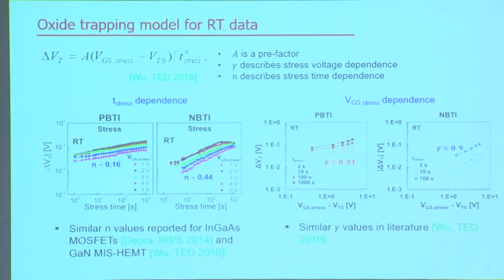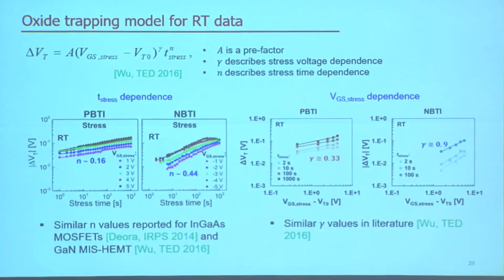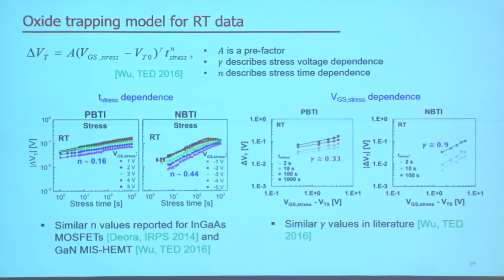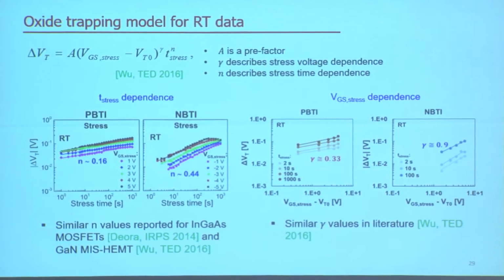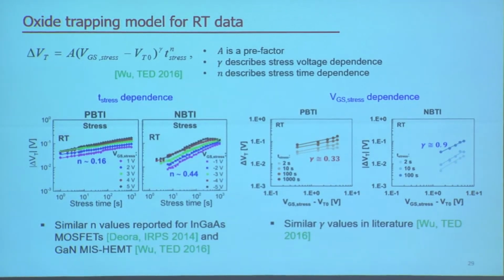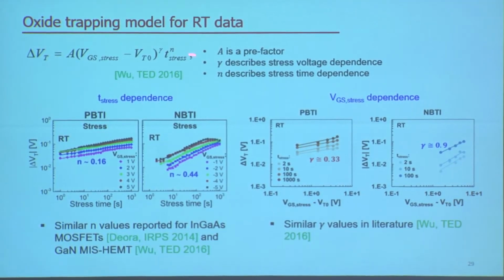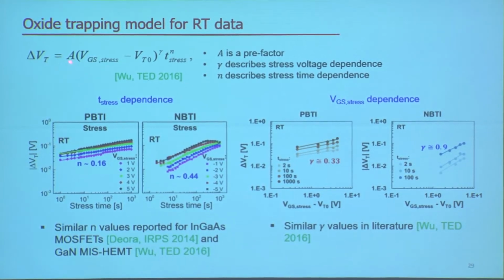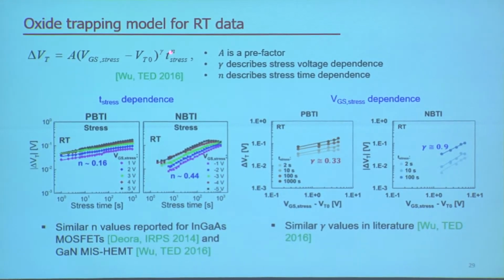So our observation at room temperature is very similar to what people have seen in other material systems, which is attributed to oxide trapping. So we use a very well-known oxide trapping model on our experimental data, with the model shown on the left side here. In this equation, A is a prefactor, gamma describes the stress voltage dependence, and N describes the stress time dependence. So we use this model on our experimental data, and on the left side, we show the stress time dependence.